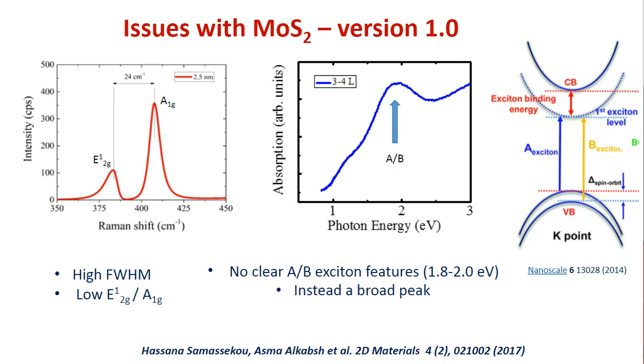And the other part, of course, which I did not quite mention here, is that our growth method was really optimized to grow 3 to 4 layers, not exactly 1 or 2 layers, because it's a very large area, across a 1 inch substrate. So we were not able to confirm that we were growing a monolayer across a 1 inch substrate, but we were able to confirm that it is 3 to 4 layers through all this characterization, particularly Raman, where we do a lot of spot checking. So we found the same E peak and the A peak over the entire sample. So this is actually a 3 to 4 layer sample, and that we confirmed from Raman, not a 3 layer, 2 layer or a 1 layer sample. But that was itself quite challenging, and that itself got a lot of mention because, again, as I said, it's still an outstanding problem to grow a uniform single layer MoS2 across such a large area substrate.